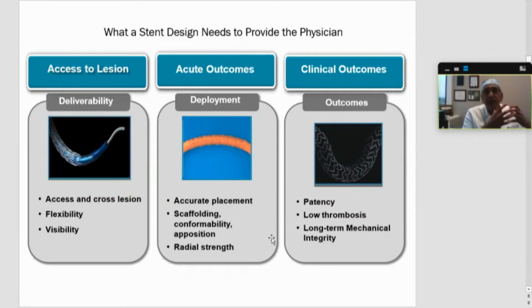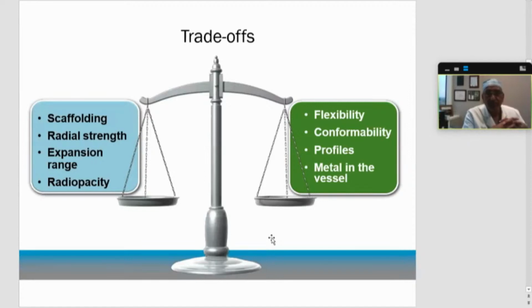Not only that, this has to be supported by clinical outcome data, whether it's patency, low stent thrombosis, or long-term mechanical integrity, which causes future restenosis and stent thrombosis. But then there are trade-offs. If you want to create a stronger scaffold, then you lose out on some of the flexibility. If you want something with higher radial strength, then it may not be as conformable. If you want to have a large expansion range, but then the profile sizes go a little bit larger, so deliverability becomes a bit harder. If you are asking for more radiopacity, then maybe that requires more metallic footprint and a thicker strut, maybe.